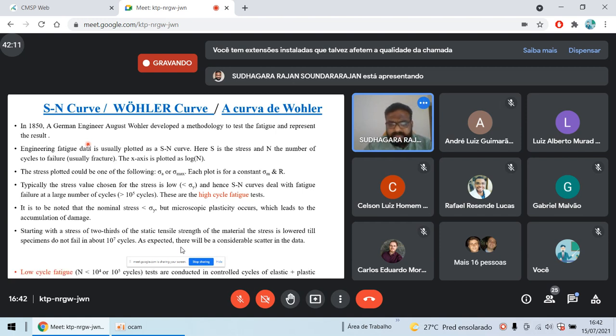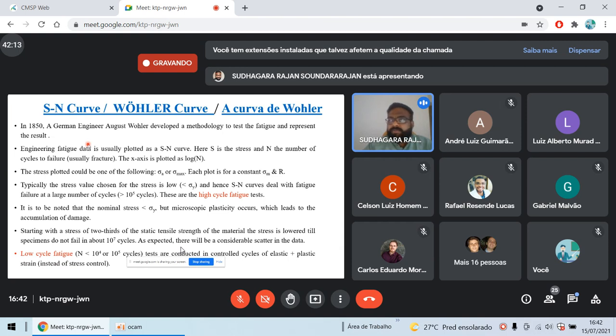Okay. So the low cycle fatigue is totally different. If the testing is done between 10^4 to 10^5 cycles or lesser than 10^4 cycles, then that testing is called low cycle fatigue testing. In this, we don't take a stress range which is below, say, the yield strength. We may take it a little higher than the yield strength. That means you can initiate the plastic flow. That's no problem in that particular low cycle fatigue testing. The entire testing, reporting, everything will differ for this. Okay, and we don't go into it as far as this class is concerned.